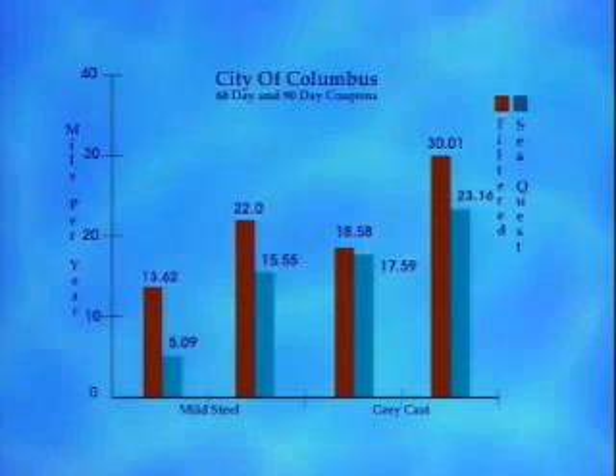Again, although we would think that the Seaquest side was more corrosive, we see from the coupons which were installed in the pipes that the Seaquest treated side was less corrosive to both mild steel and gray cast than the pH treated side. The only conclusion to be drawn is that Seaquest without pH control is a better corrosion control product than the raised pH levels.